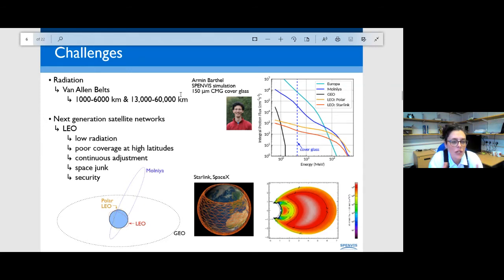Now, one of the ways in which we can avoid these high radiation environments is actually going into a low Earth orbit, which is also known as LEO. Now you can see a plot here in the top right, showing integral proton flux. This was compiled by my student Armin Bartel using data from SPENVIS, which is a European database of space radiation environments. You can see that the LEO environment is relatively low in terms of radiation exposure, which makes it quite attractive for many of these networks.